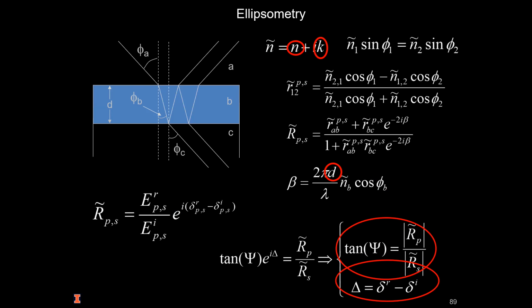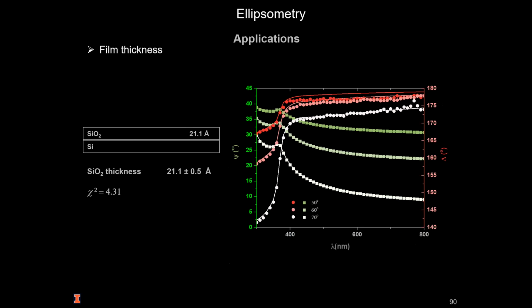One of the simplest examples of the application of ellipsometry as a characterization technique, and one of the most utilized as well, is the determination of the thickness of a thin transparent film. In this case, we used it to measure the thickness of a native silicon dioxide layer on a silicon substrate. From the fit, using tabulated values for optical constants of silicon dioxide and silicon, we could determine the thickness of the oxide layer to be about 2 nanometers.